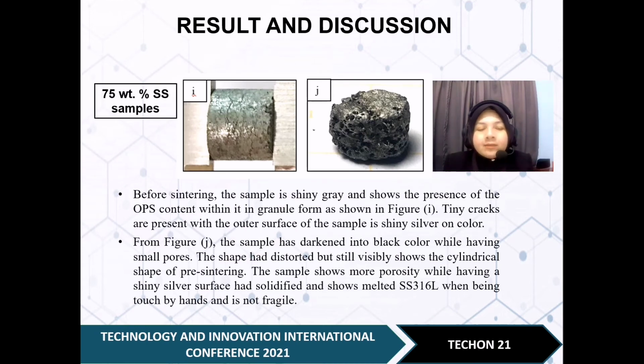And the next one is the 75% stainless steel sample. This is the highest content of stainless steel powder in my research. We can see that it also has a crack in the green body before sintering, but after sintering we can't see the crack. The sample is fully solidified. From the figure, the sample has darkened into black color while having small pores. Compared to the previous samples, these samples have few, small pores. The shape has distorted but still visibly shows the cylindrical shape of pre-sintering.